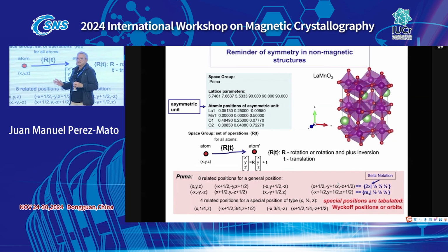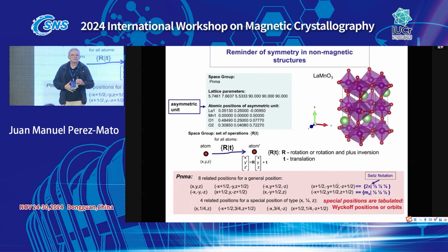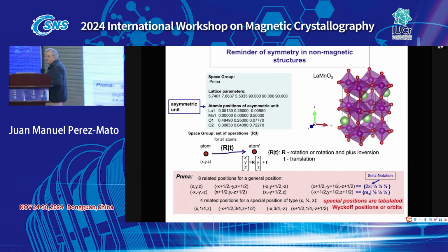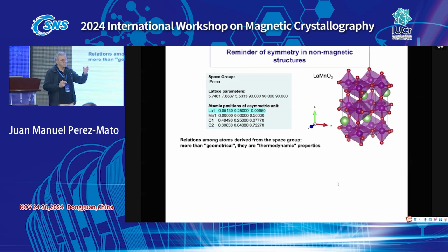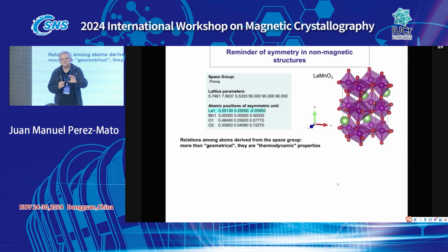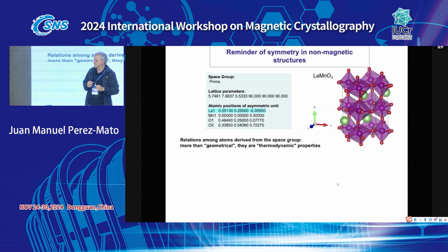It is very important to be clear on this, because if we don't have this, we cannot go much further. Now what I want to stress is that with these geometrical relations, we are saying, okay, just give me one atom, and if you tell me what the space group is, I can construct from this atomic position all the atomic positions which we say are symmetry equivalent. They are symmetry equivalent because I can obtain them from this one by applying these operations and by applying the lattice translations which are defined by the unit cell. Because the unit cell is just telling me everything is repeated according to these A, B, C vectors defined by the unit cell, which defines the lattice.